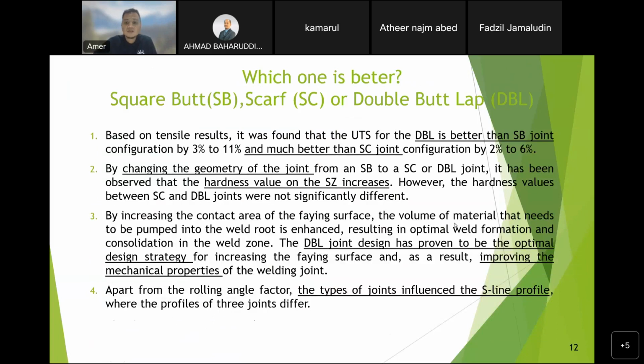By changing the geometry of the joint from square butt to scarf joint or double butt lap joint, it has been observed that the hardness value of the stir zone increased. However, the hardness value between scarf and double butt lap joint were not significantly different.